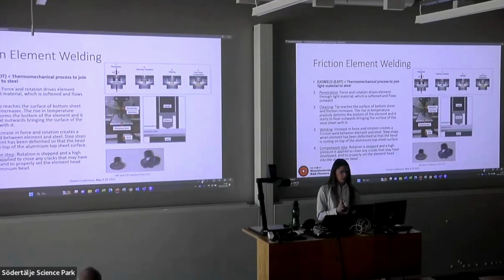And then if we take a look at friction element welding, the process developed by Arnold. It is a thermomechanical process to join lightweight material to steel. So in this case, you place your lightweight material on top and your steel on the bottom. In this process, you mainly set rotation and friction, and then you progress in the program by position of the element. You predetermine a distance, and when it is reached, the next step is initiated.